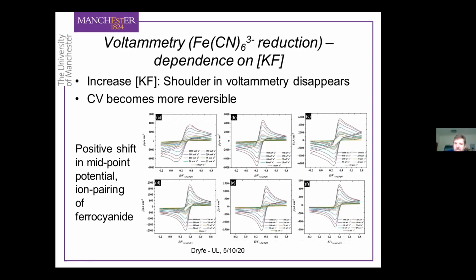So that's the capacitive response. If we can even do a simple CV experiment, as I've mentioned before, the ferri-ferrocyanide redox couple does not behave that well on basal plane graphite. As I talked about with the data I presented from Unwin's group, it's not a very reversible couple, at least after a few cycles. You see a fairly messy response.